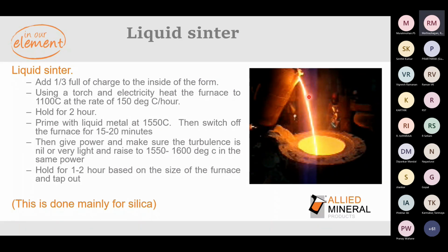Prime the liquid metal at 1500 degrees Celsius from the other furnace, so that you get clean liquid metal, and from that furnace you can bring it into this sintering furnace. After tapping, switch off the furnace for 15 to 20 minutes so there's not much turbulence because of the power. Then slowly raise the temperature, because there will be a drop in temperature, to 1550 to 1600 degrees Celsius and hold for 2 hours. As I said before, we recommend this liquid sintering since it gives a clean sintering to your lining with no slag attack to the main working lining or no saturation in the initial lining.